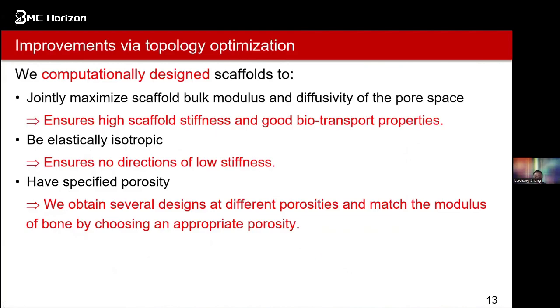So for that, we use topology optimization to design a scaffold that would have a maximum modulus for its weight and interconnected porosity. In addition, the design needed to be elastically isotropic and be able to be made in a range of different solid fractions. So we proposed a computationally designed scaffold to jointly maximize scaffold bulk modulus and diffusivities of the pore space. This can ensure high scaffold stiffness and good transport properties. And also, that's very important because we try to make it elastically isotropic. Otherwise, the patient will not have a good feeling.